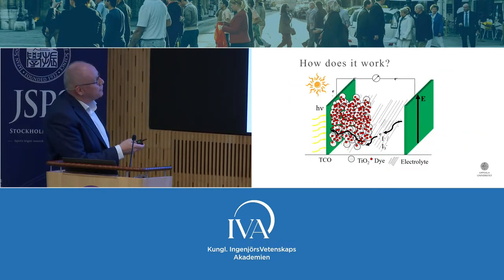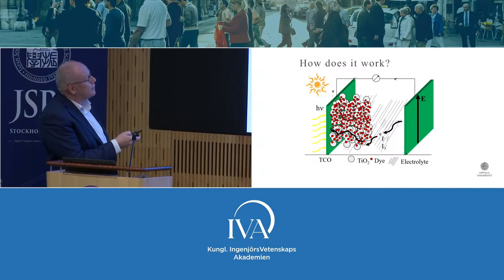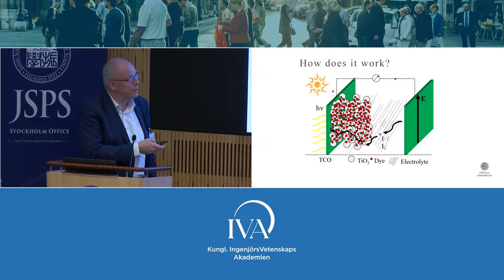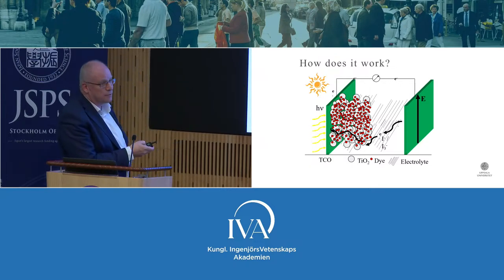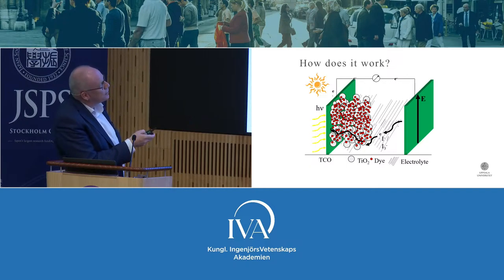This is how it works a little bit. You have a nanostructured, highly porous, high surface area electrode. That's the trick. So you can have a monolayer of dye at a high amount, so to speak. So that's the photoelectrode. You impregnate it with the electrolyte solvent and the iodide, for example. So you shine light, you excite the dye molecule, you inject an electron into the titanium dioxide particle. This was a mystery when it was started. People even didn't believe it should work. But I will not go into that. But it's a lot of fun to develop how this solar cell actually works. The transport goes through all these particles to the contact, does electrical work, goes to the plus, the cathode, and then you reduce the electrolyte and you bring the electron back to the dye and you close the circuit.